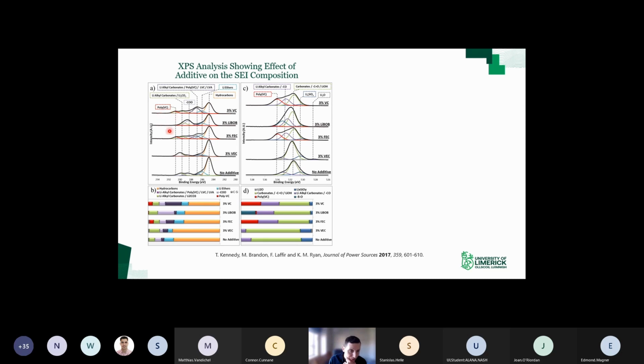For VC and FEC, we found it to be in there in around 6% concentration by weight in the SEI layer. For LiBOB, it's not obvious here, but we did find it as well. It was in there in about 1% concentration, so that explained why that did have a high capacity retention. For LiBOB, the capacity retention can also be explained by some other compounds that we found in the SEI layer. So boron semicarbonates, for example, that are less prone to dissolution. So not only with the SEI layer do you get cracking, but as you discharge to 1.5 volts, for example, in a half cell, you can get dissolution of the SEI layer. And LiBOB forms those boron semicarbonates that are less prone to dissolution. So that explained why this one had a high capacity retention, even though the amount of poly-VC was much less than in the VC and the FEC.